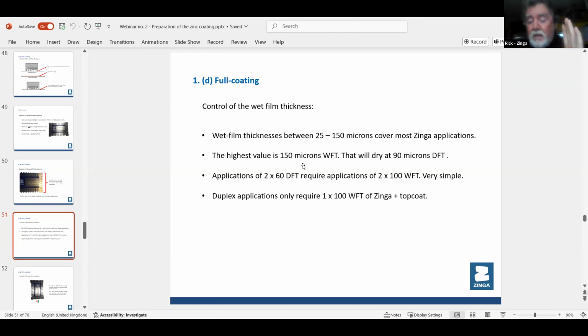That's one of the big charms of Zinga. Whether you apply 2, 3, 4, 5 layers of Zinga, if you X-ray it, there's only one layer on the steel, and that's why we have such a powerful electron flow. The current's flowing very strongly because it's one layer. It doesn't dry into different layers like epoxies do.